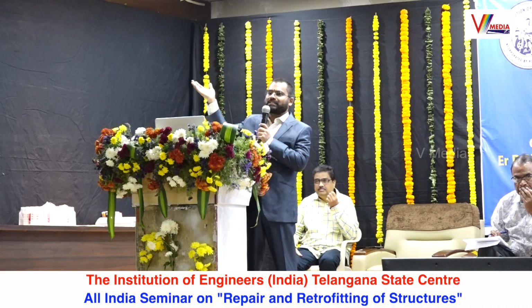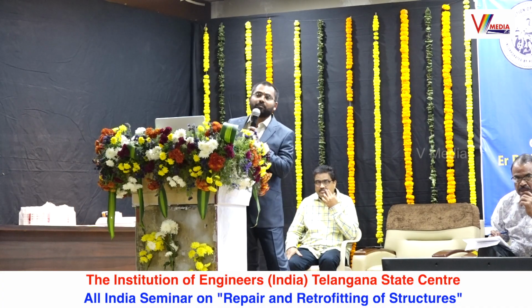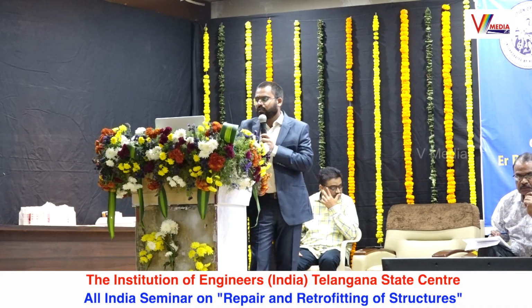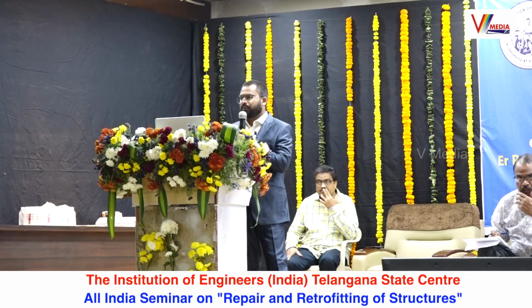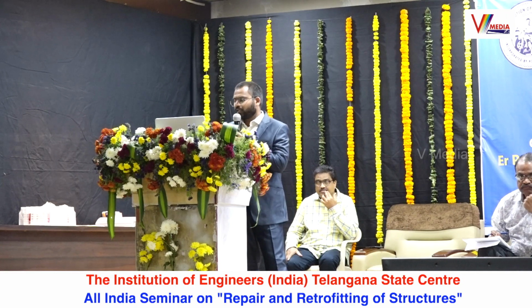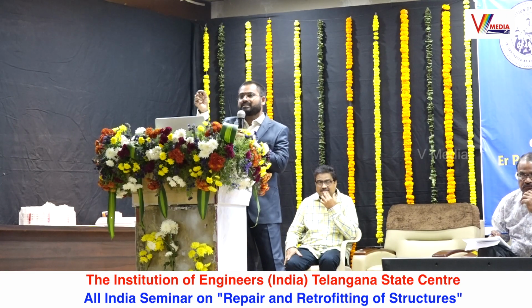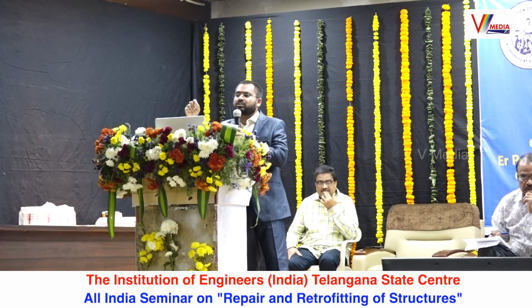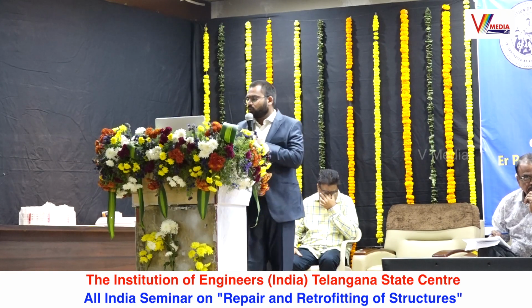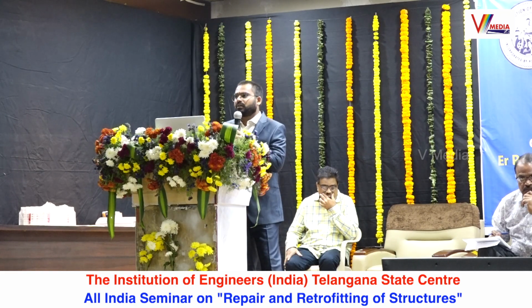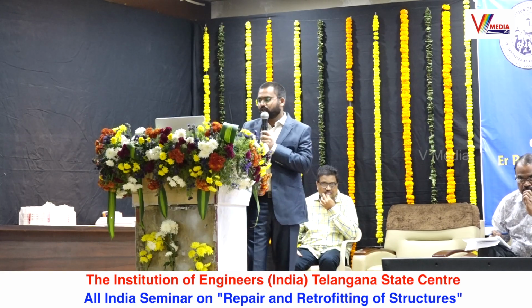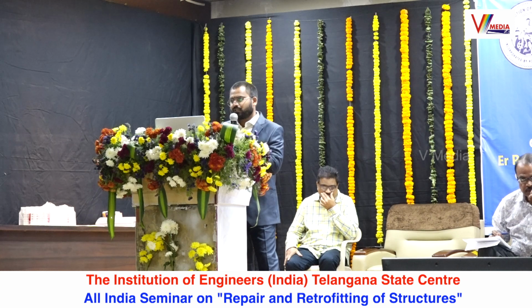The transmitter and receiver are placed away from the crack, and the pulse velocity is recorded the first time. The second time, the transmitter and receiver are placed in such a way that the crack is at the center. In this case, the pulse velocity will be lower. Then you have a formula. You can substitute the values and estimate the depth of the crack. So this can also be done using the ultrasonic test.